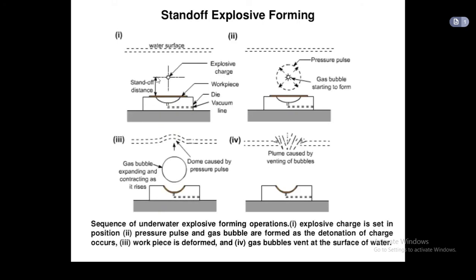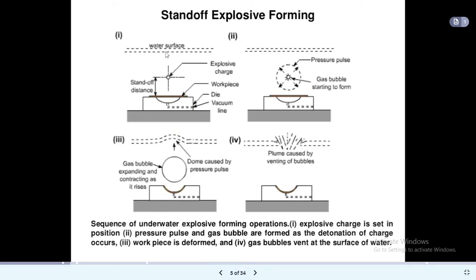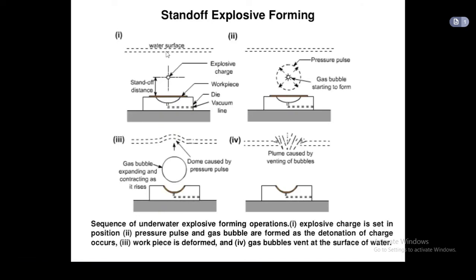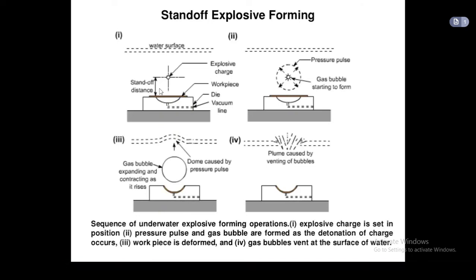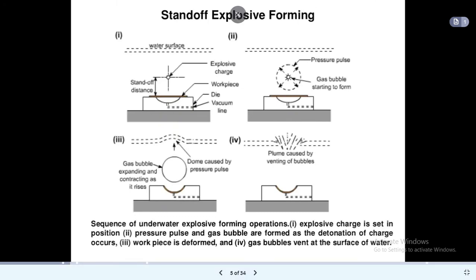Now next is the hydrostatic head. The hydrostatic head is the distance from the explosive up to the water surface, and generally it is taken as 2 times the S. If we take the hydrostatic head as H, then it is equal to 2 times the S. Okay.